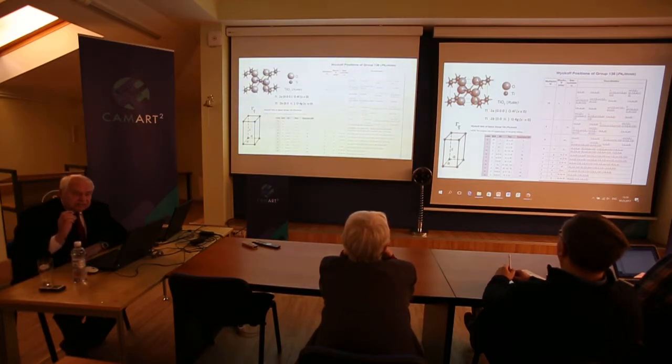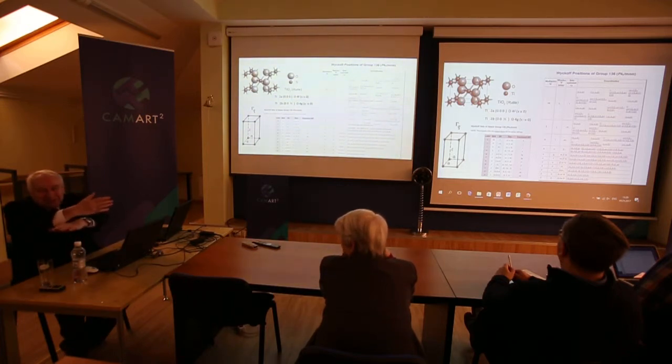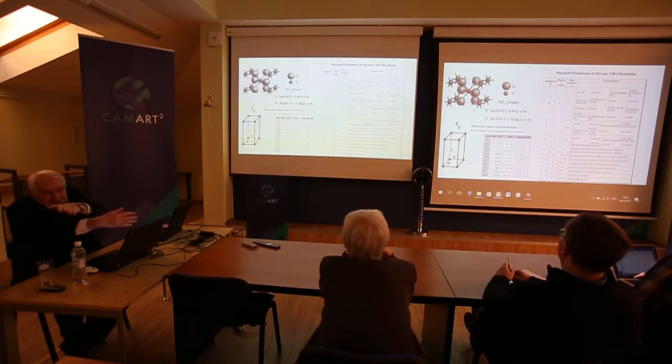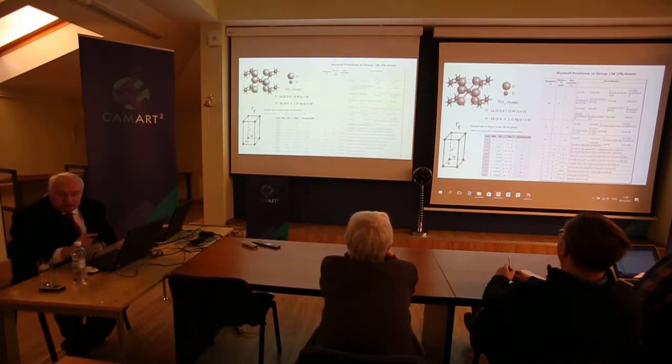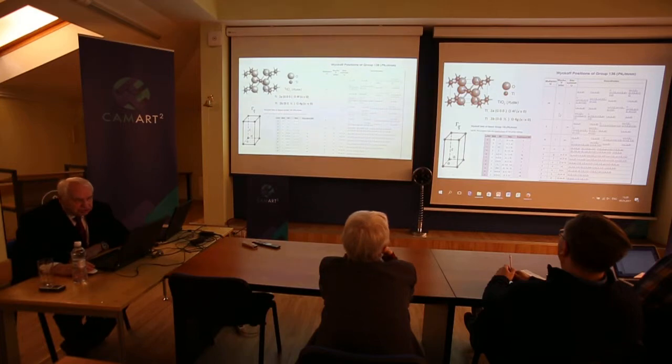So this fourth order axis is a screw axis, and it is due to the oxygens, because, excuse me, as I show, these diagonals are crossed, and when you rotate, you are in an empty position, and you need to move downstairs or upstairs. Doesn't matter, because this is translation.